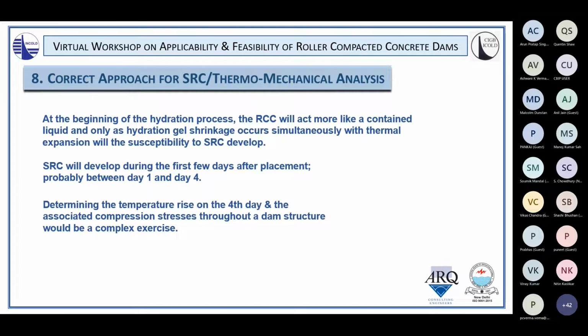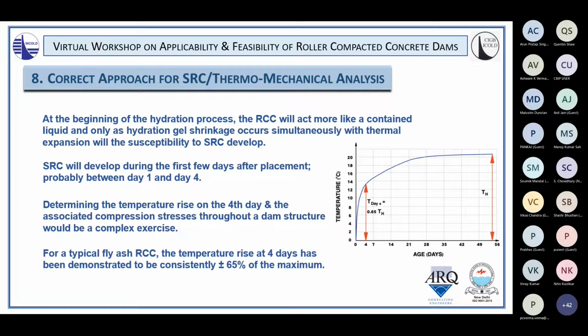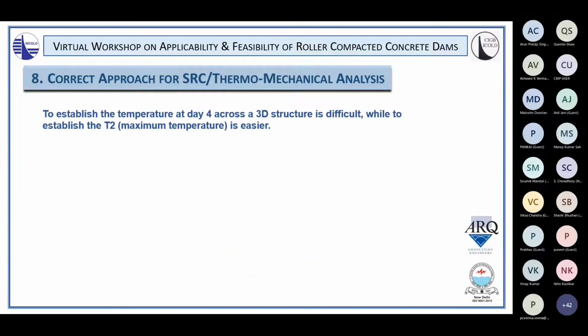Determining the temperature rise on the 4th day throughout an entire dam structure and establishing the associated compression stresses at that time at those particular points throughout a dam would be a very complicated and complex exercise. For a typical fly ash RCC, the temperature rise at day 4 has been demonstrated to be consistently plus or minus 65% of the maximum hydration temperature rise, whether that be adiabatic or whether it be conditions due to some exposure of the surface. So in view of the fact that establishing temperatures at day 4 across the entire dam structure is very difficult, it's much easier to establish the maximum temperature, the maximum temperature at the peak of hydration, the T2 temperature.